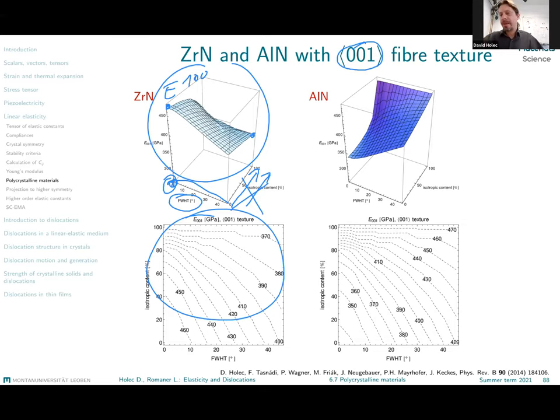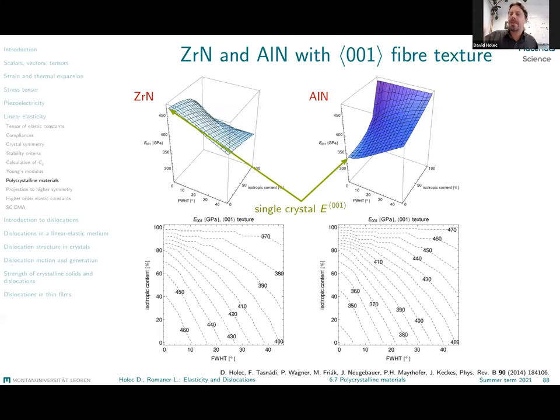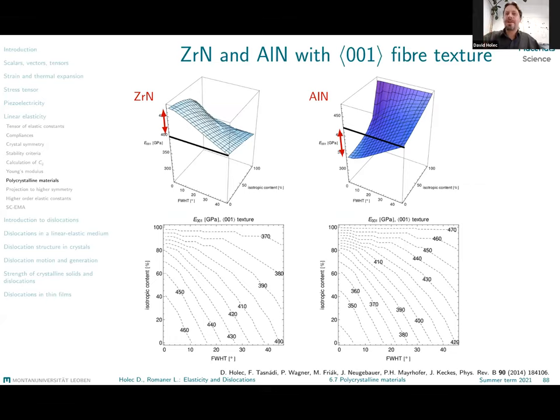What we see from here, now I will probably wait again before the images load. What we would see here is that based on your real microstructure, depending therefore on the misorientation of your grains, the amount of the grain boundary phase, and of course, then depending on whether you have zirconium nitride or aluminium nitride, you can have really large differences between the resulting predicted values of Young's modulus. The differences in this particular case can be as large as 150 gigapascal. So here we see the large differences going from 380 to 430 gigapascal, depending on the microstructure.